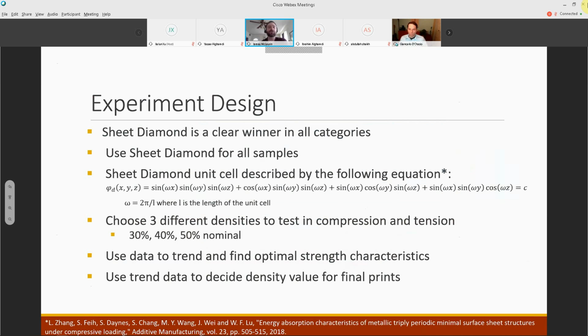That sort of changed the scope of our project a little bit. We originally were going to use different lattice structures and test them out, but we decided we were going to go with different densities of the sheet diamond structure, since we found it to be much greater in our research than the other structures. You can see here we've got the equation for the sheet diamond structure, a lot of cosine and sine waves, so a very curved structure. What we decided to use is a data trend based on densities and strength characteristics to decide which density we would use for the final rover print.